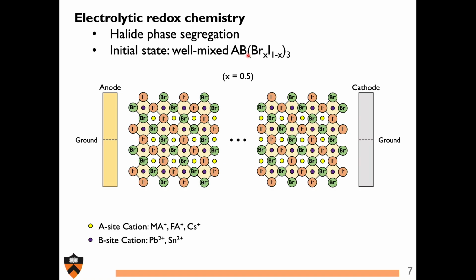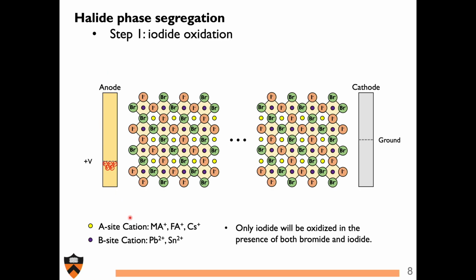And this is fully reversible. You can go back and collapse to the nearly well-mixed AB mixed halide system. And so here's how it works. I have an anode and a cathode. Anode's on the left, cathode's on the right, and I have a well-mixed x equals 0.5 halide system in between. If I put an anodic potential on this, so a potential difference between the anode and cathode, as I mentioned, the first thing that we can expect is iodide can get oxidized. So holes basically oxidizing these surface iodide atoms, the ones on the left here.